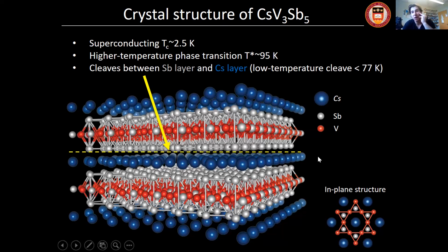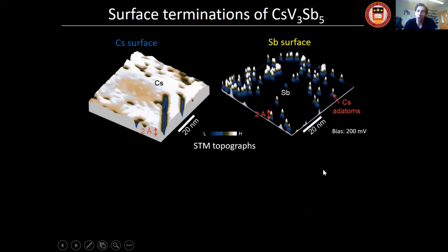But if we did this, we can estimate the cleaving temperature based on how hot the STM gets once you put the holder back inside. This was the lowest temperature we could achieve, and it gave us pretty good cleaves, with very large flat areas that we can investigate. If you try to cleave this at room temperature, for instance, it will be completely reconstructed. This is not unique to this class of materials, but maybe related to the alkali nature of this layer. In any case, we can either image this alkali metal surface or the antimony surface, and these are indeed the two surfaces we get.